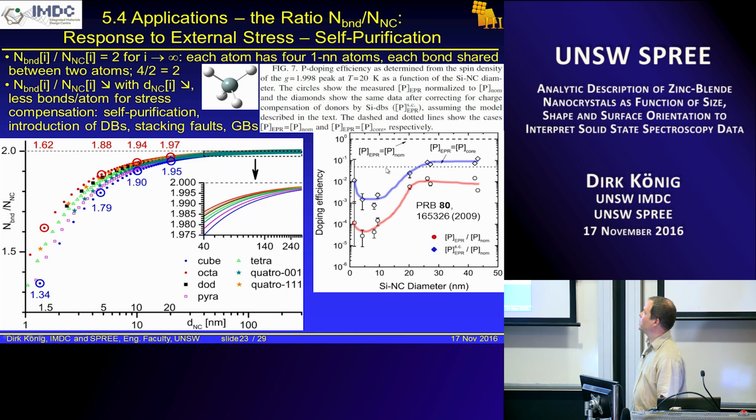First, they etched off the oxide, and that already removed 95% of phosphorus. And the phosphorus atoms with an unpaired electron on the lattice site are shown by this red line here. And we see between 20 and 10 nanometers that there's a decrease of 2 orders of magnitude. So it doesn't make sense actually to go below 20 nanometers if you want to dope nanocrystals. We all know that actually from polycrystalline silicon cells, the huge majority of the dopants ends up at the grain boundaries. That's the same effect. They kind of get pushed out.